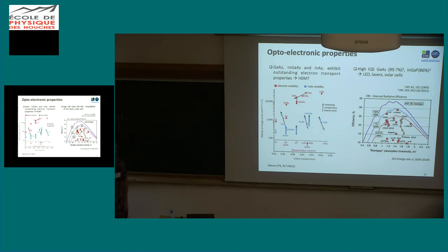The other interesting point that is very useful for solar cells or LEDs is the fact that they feature extremely high internal quantum efficiency. The internal quantum efficiency is the ratio between the photogenerated carriers and the photons that are actually absorbed inside the solar cell. So here you have a plot from a nice paper from Martin Green, where he plotted the Shockley-Queisser limit in the case of 100% external radiative efficiency. In this case, it's the ratio between the impinging photons and the photogenerated carriers, so you have to absorb them first. Whenever your material has a lower external radiative efficiency, you can expect a degraded Shockley-Queisser limit.